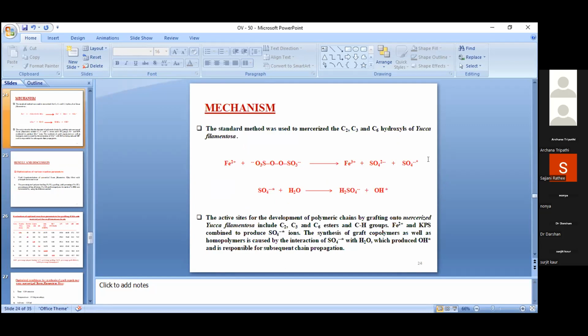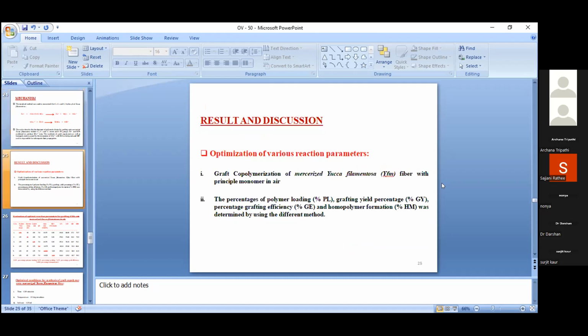Mechanism. The standard method is used to mercerize the C2, C3, C6 hydroxyl of yucca filamentosa. The active sites for the development of polymeric chains by grafting onto mercerized yucca filamentosa include C2, C3, and C6 ester and CH groups. Ferrous and KPS combine to produce an SO4 radical ion. The synthesis of graft copolymer as well as the homopolymer is caused by the interaction of SO4 and water with the produced OH radical, and is responsible for further chain propagation.